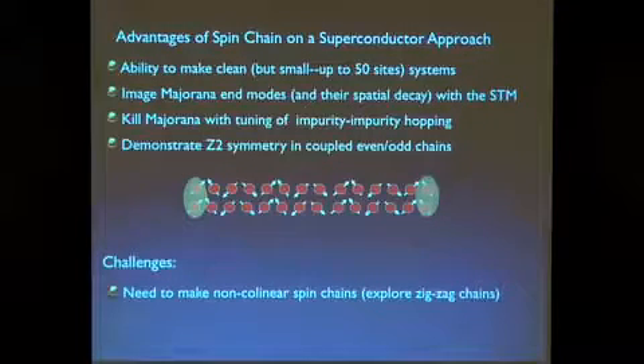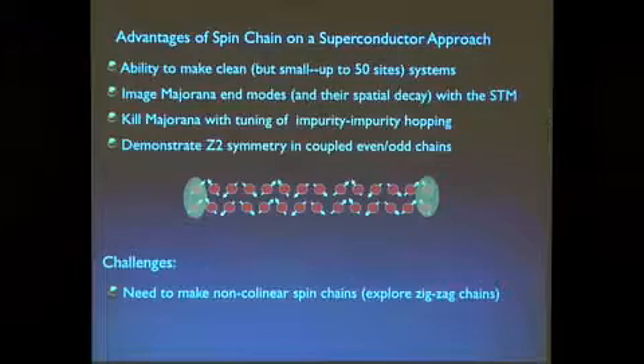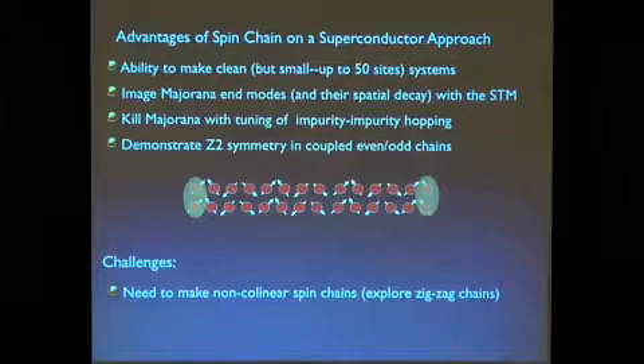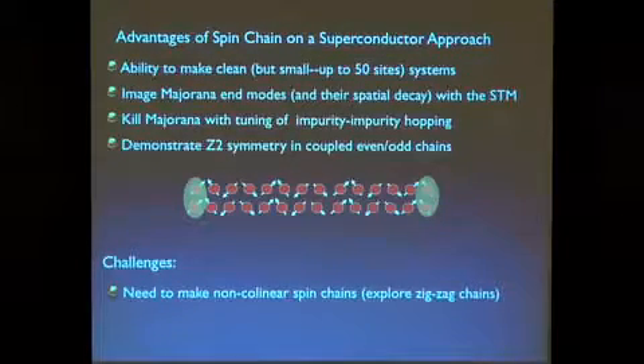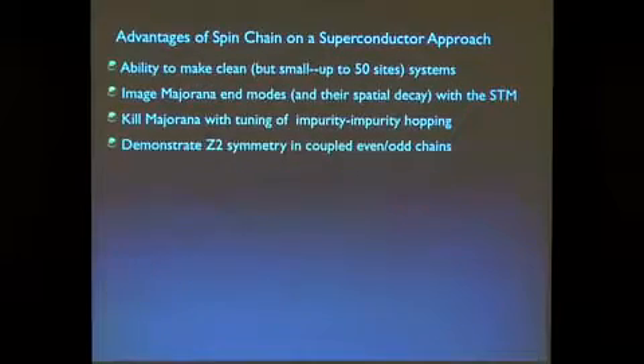So there is a challenge which I didn't want to get into, but it has to do with the spin texture. And this spin texture is critical, but we have ideas in which you can perhaps explore not just a linear chain, but zigzag chains in order to create a handedness to the spin, as I've drawn it here. In the experiment, the data you show has a spin texture?